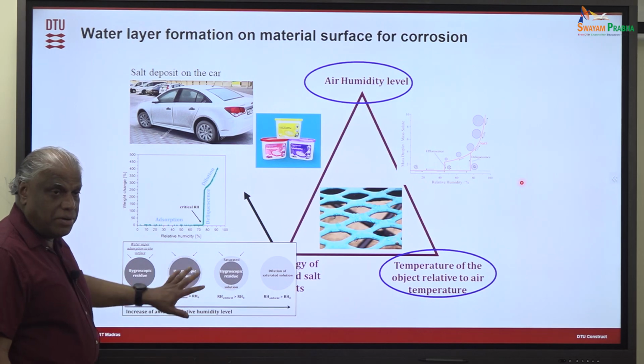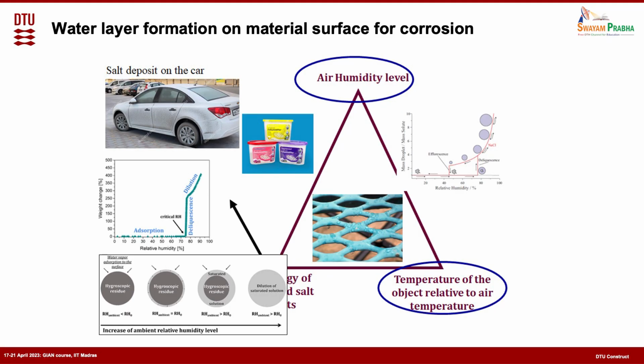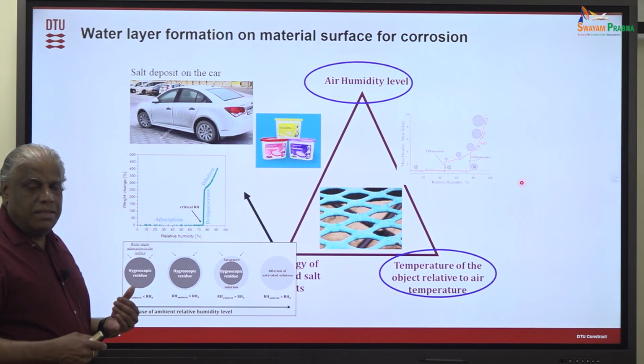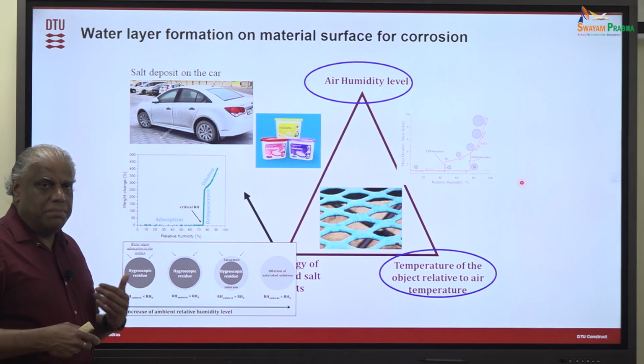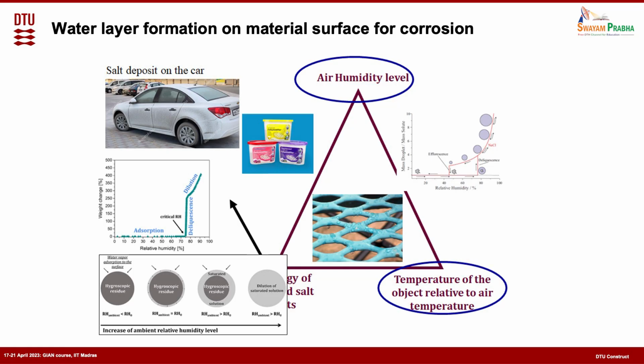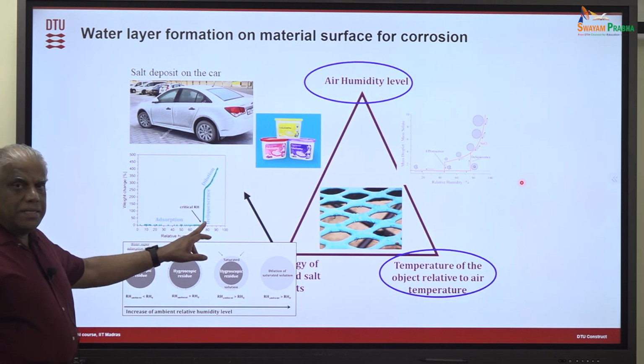Deliquescent property is a thermodynamic property which is there for all hygroscopic substances. Any hygroscopic substance you take, there is a stability. It is stable as a solid and stable in solution, and this is determined, again coming to the free energy part, by a particular humidity level at which this substance will start dissolving.